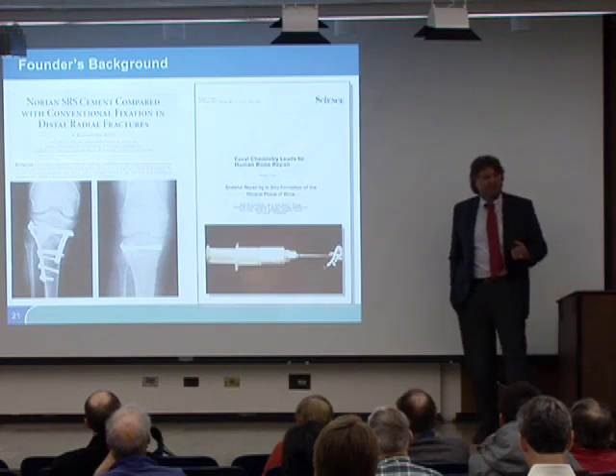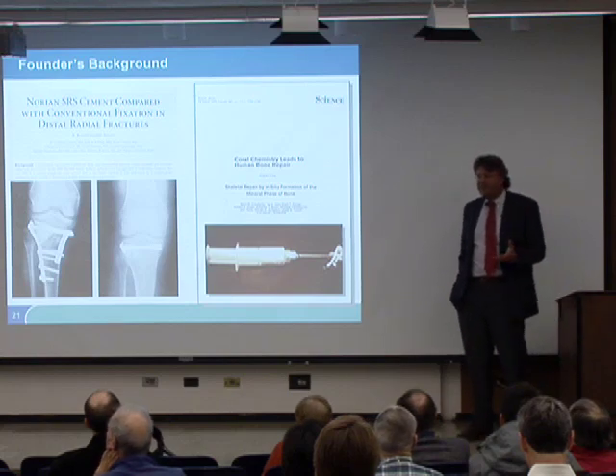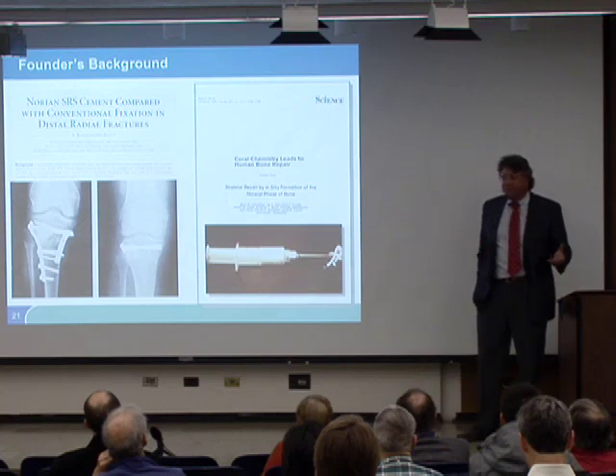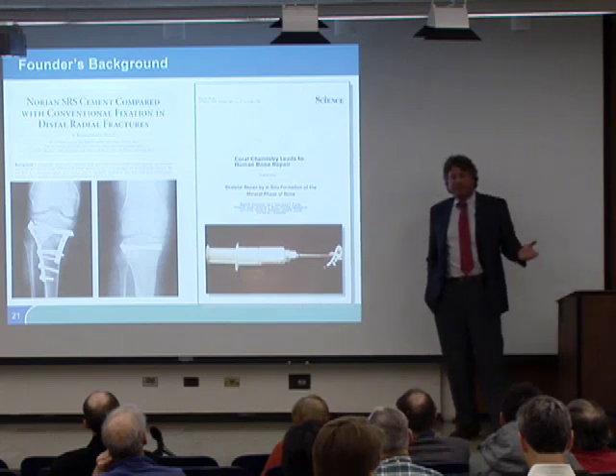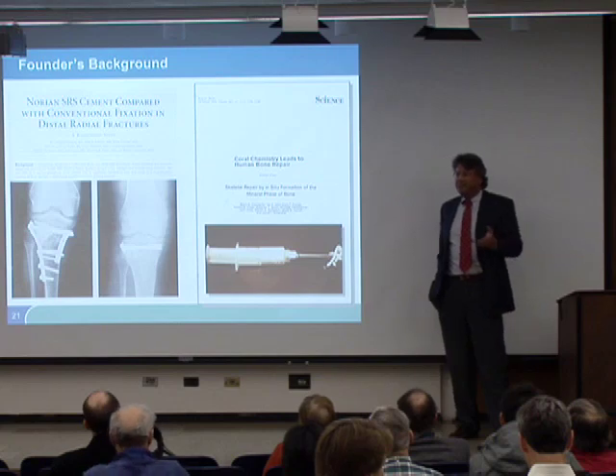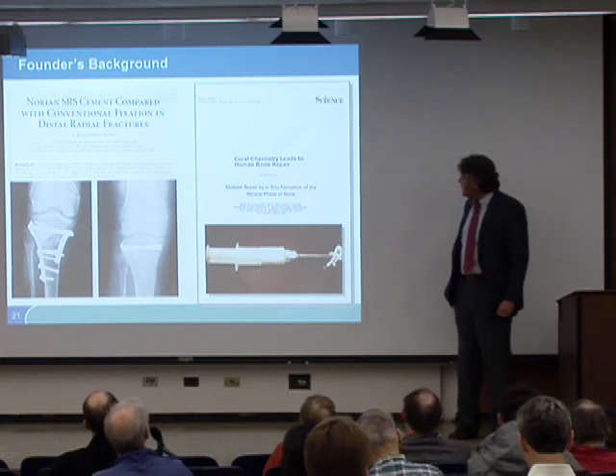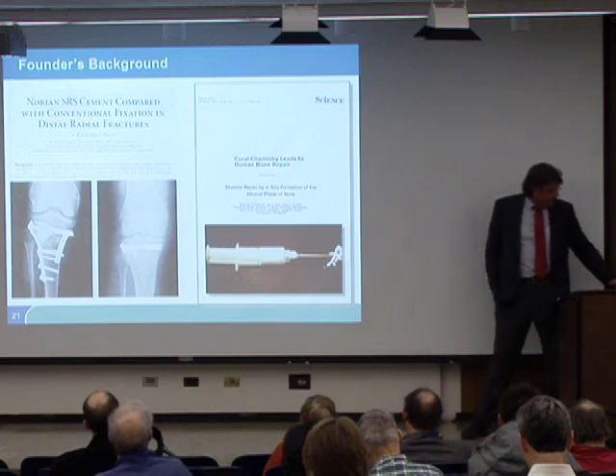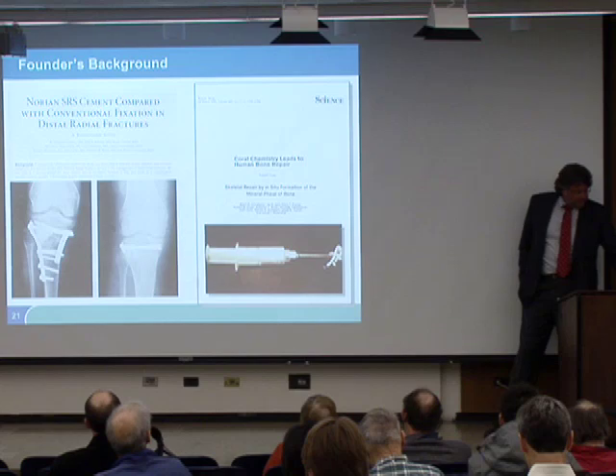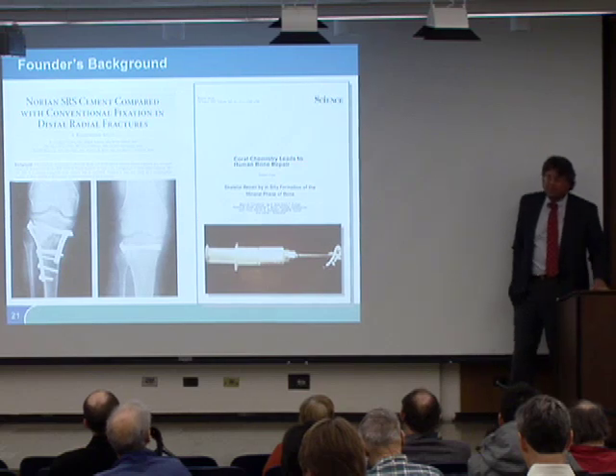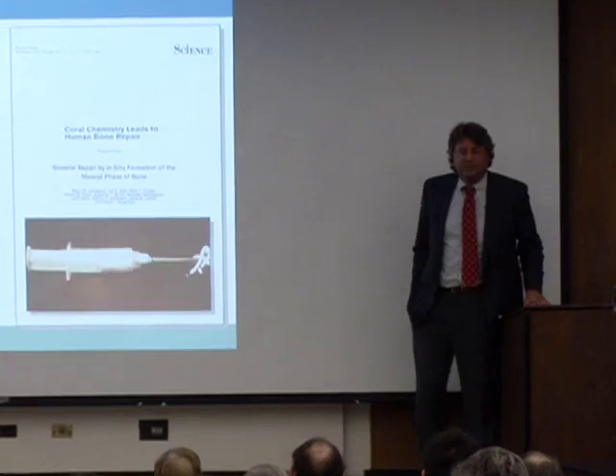So just to give you a feeling for it, these cements would achieve 10 or 15,000 PSI compressive strength before you even pulled the patient off the table. The sidewalk out here might reach 5,000 PSI after 28 days. So I was over here at the Woods Institute, and I learned that the production of Portland cement was considered the third largest source of anthropogenic CO2, which I should have known, but I didn't know that. You know, when you calcine limestone, it makes sense.